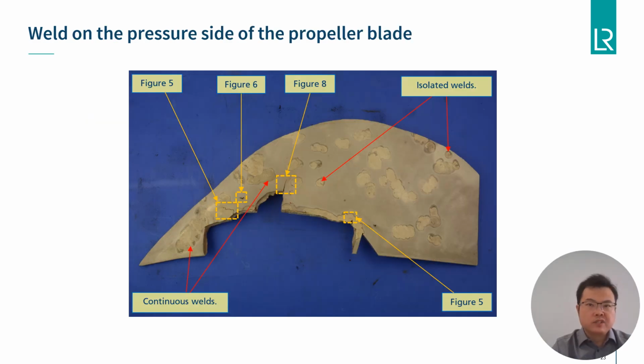Let's look at some detailed features from this picture, which is the pressure side of the blade. The fracture path is perpendicular to the trailing edge for approximately 30 millimeters before a rather sharp 90-degree turn. Then the fracture follows a linear route parallel to the trailing edge for around 200 millimeters, apart from a central curved fracture path approximately 40 millimeters wide.